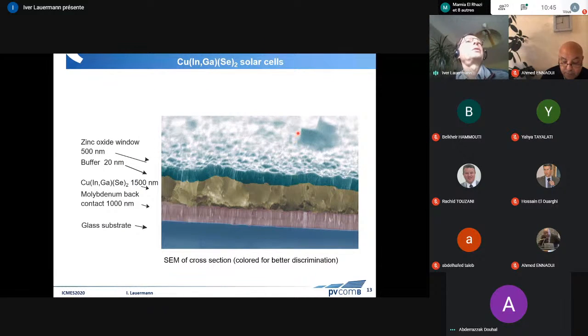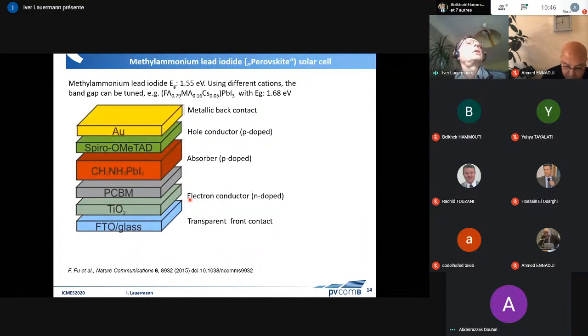And if we now talk about the two individual technologies that we're utilizing, as a bottom cell, low band gap, we use the well-known copper indium gallium diselenide, which is a commercial product already. It's a thin film device. And for the top cell, we're using these fairly recent methyl ammonium lead iodide based or perovskite solar cells. Now, the actual absorber, which initially was methyl ammonium lead iodide, can be modified in this stack. We can replace the cations and the anions, and that way we can change the band gap and choose the optimum material for a tandem solar cell.